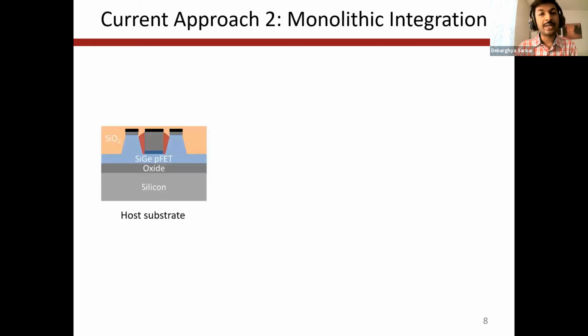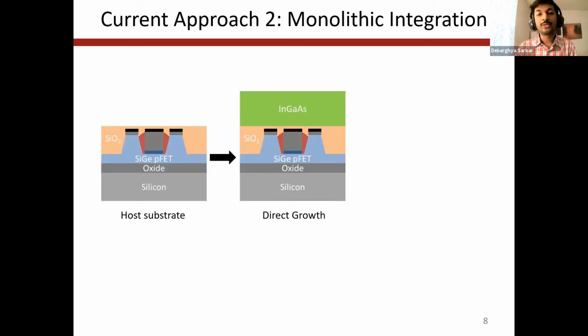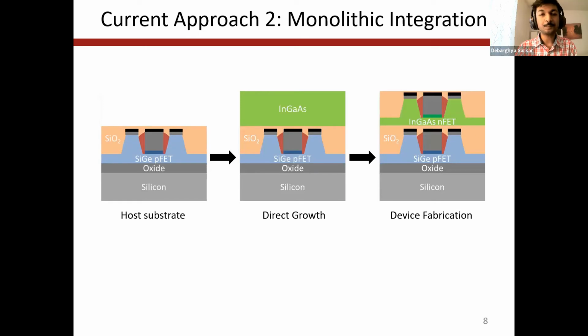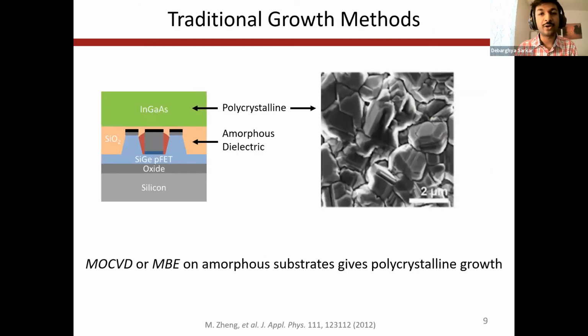The other approach is called monolithic integration, where the host substrate is taken and materials are directly grown on top of the host substrate from which devices are fabricated. Now, as you might expect, this approach is more economic and scalable by orders of magnitude, but traditional vapor phase growth methods like MOCVD or MBE, when used to grow on amorphous substrates, which is essentially the topmost layer in an integrated circuit, would lead to polycrystalline material growth. And polycrystalline materials are unsuitable for high performance devices.